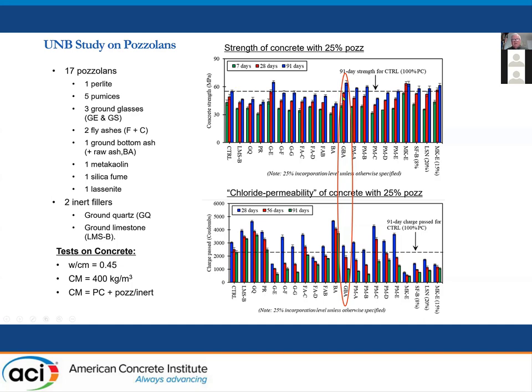And you can see that by 28 days, it's reached the same strength, and at 90 days, it's exceeded the strength of the Portland cement control. And the Coulomb values, again, are going down with age, and they're lower than the Portland cement control at all ages, even at 7 days.